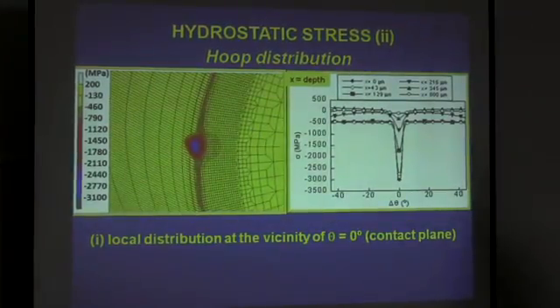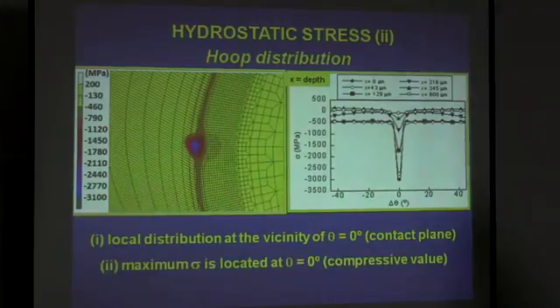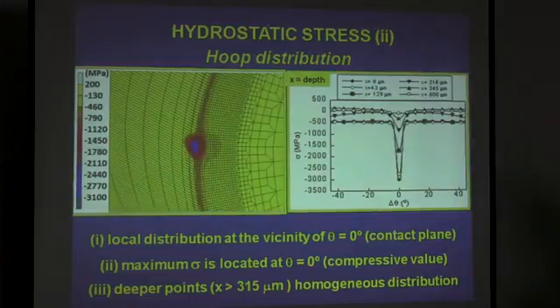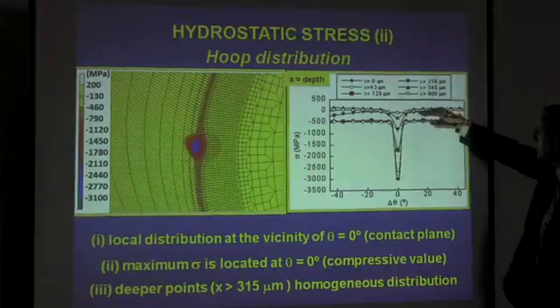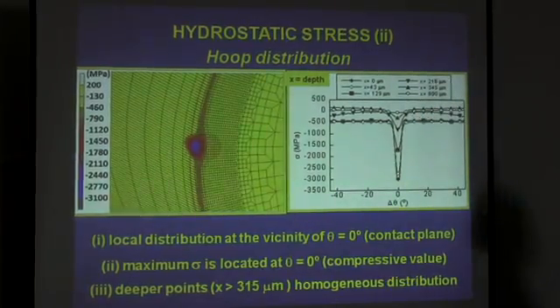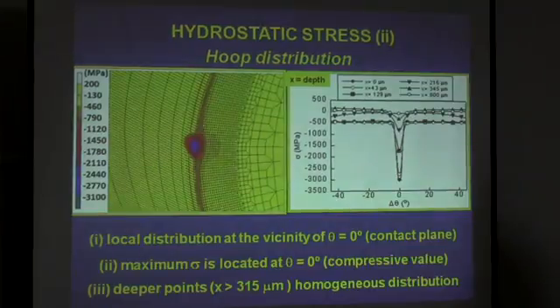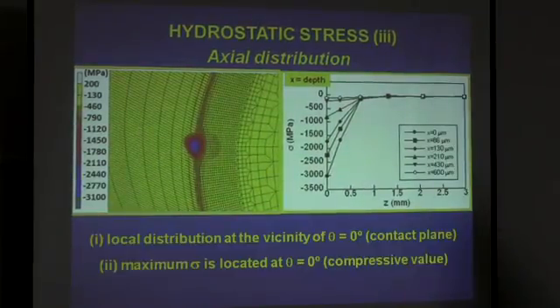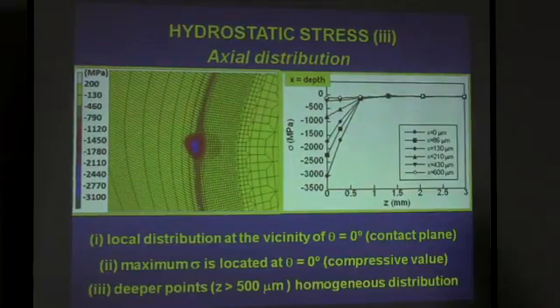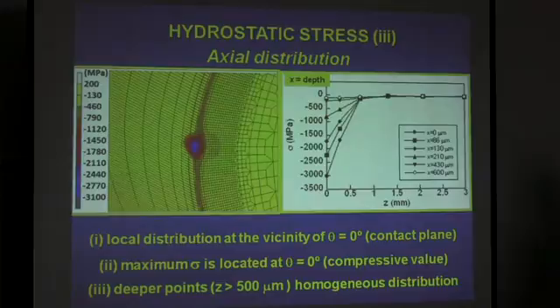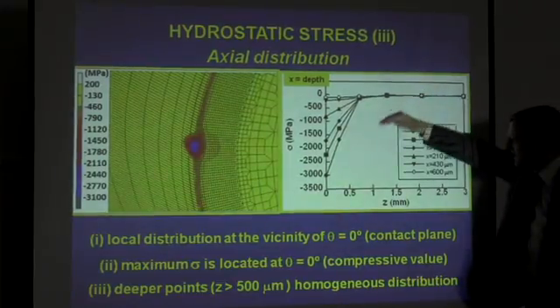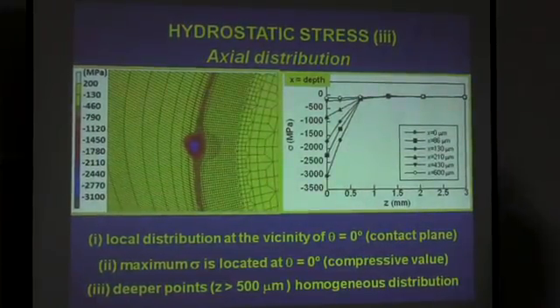Local distribution in the vicinity of the contact plane: the maximum is located exactly at the contact plane, at zero, and at deeper points, 315 micrometers, a homogeneous distribution. For different distances, we have a homogeneous distribution outside this area. With regard to the axial distribution, the maximum is at 0 degrees, and at deeper points, a homogeneous distribution. Also, it vanishes with the depth. And let's go to the next slide.